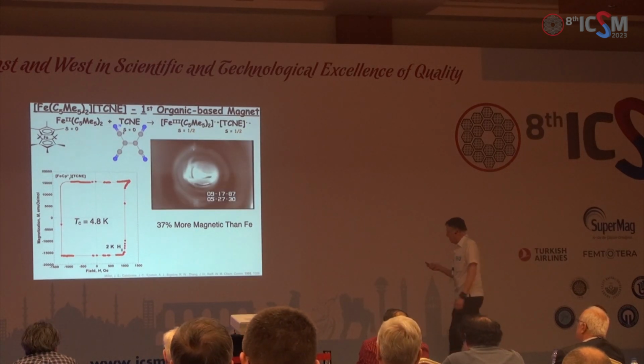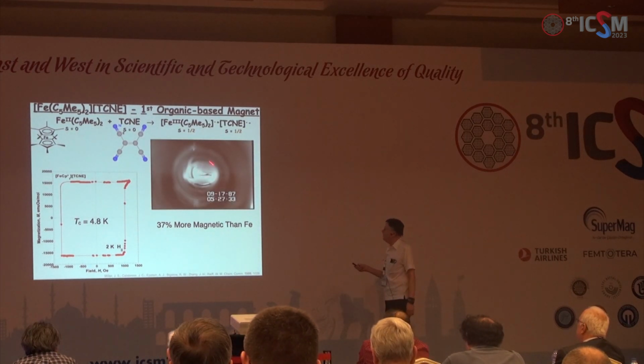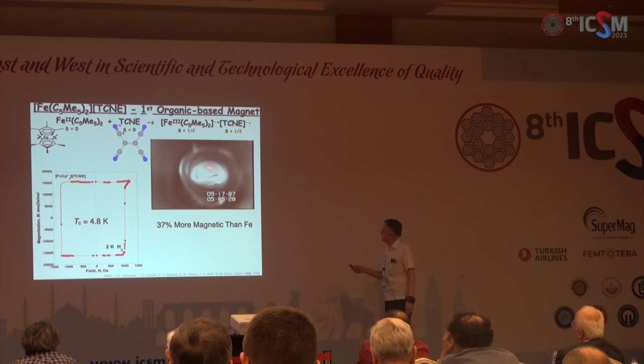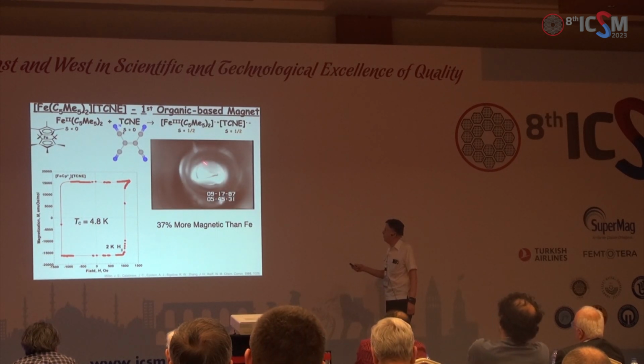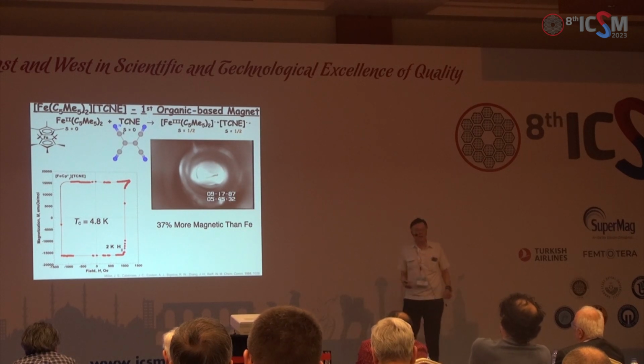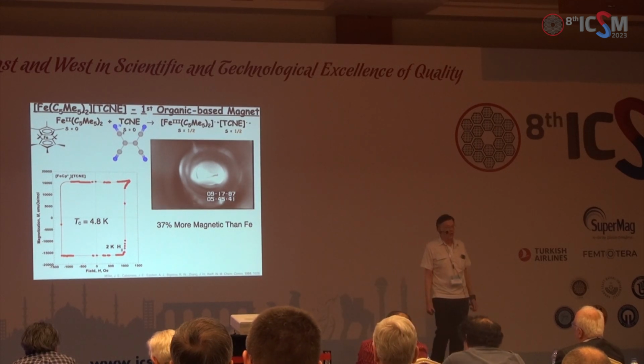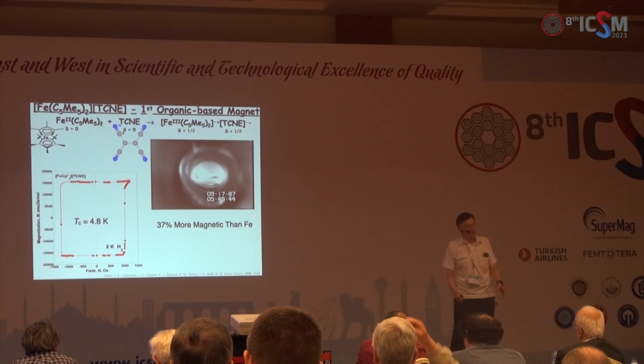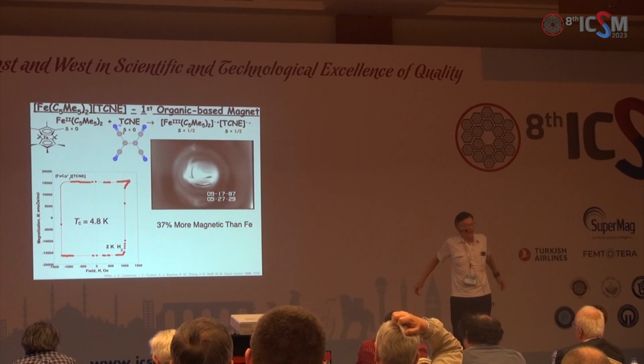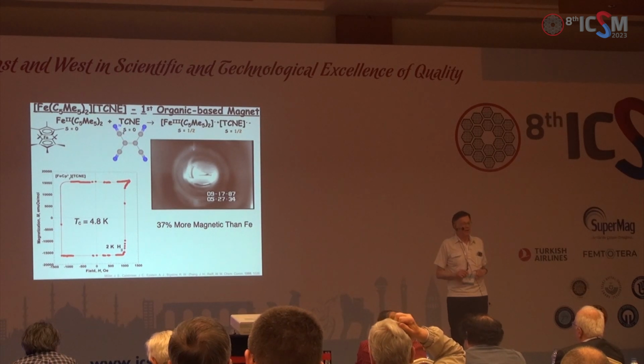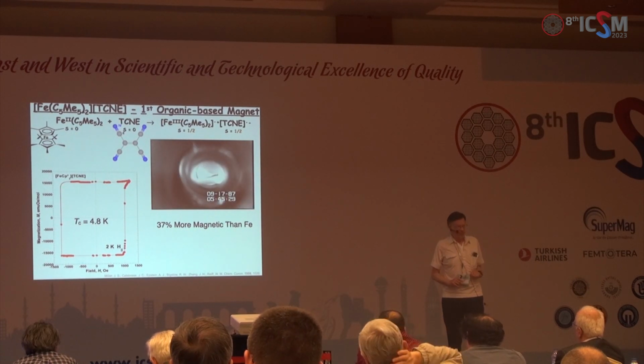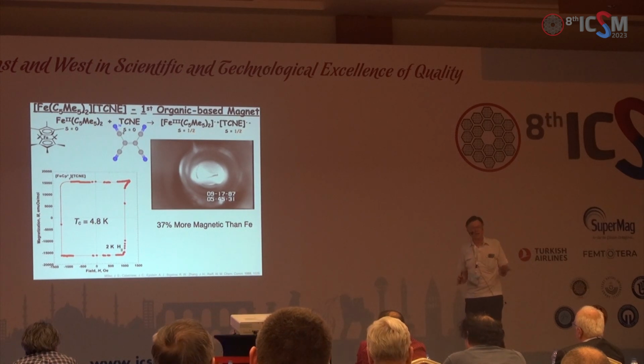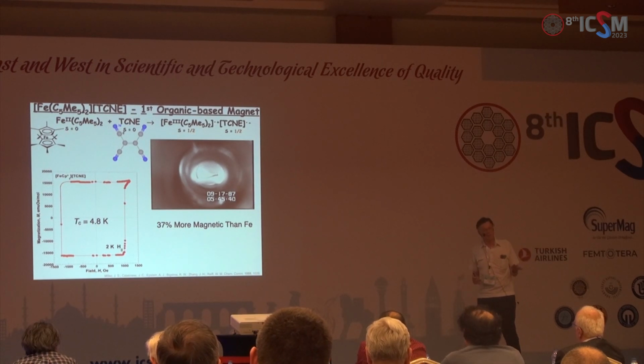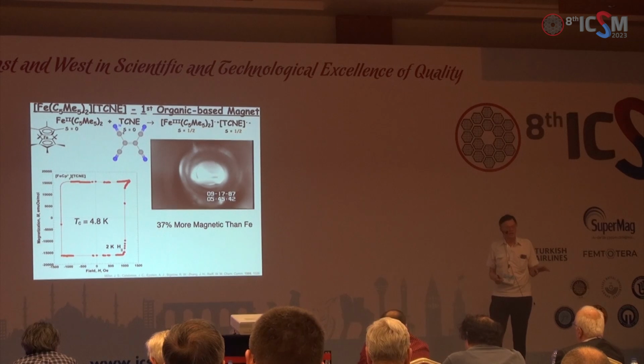Here is a pellet of it in a liquid helium dewar with a cobalt samarium magnet. You pour in liquid helium, it gets cold. When it gets cold, it goes below TC. When it goes below TC, it's highly magnetic and jumps up to the magnet. Then you let the helium boil away, it gets warm, and it plops down. So this demonstrates that this molecular material, which is more ionic than sodium chloride, is a magnet.